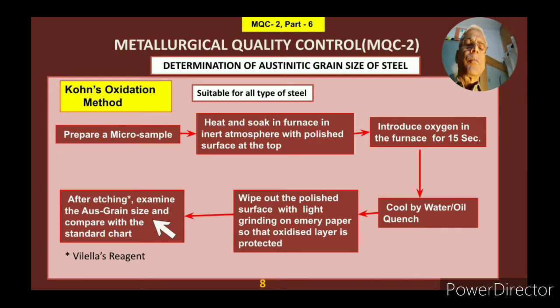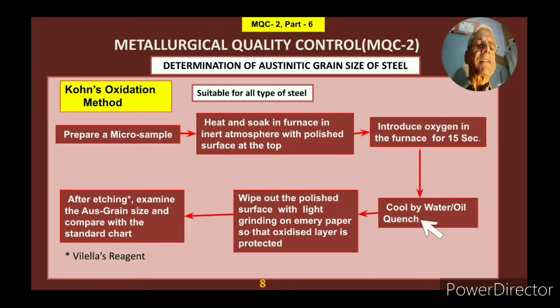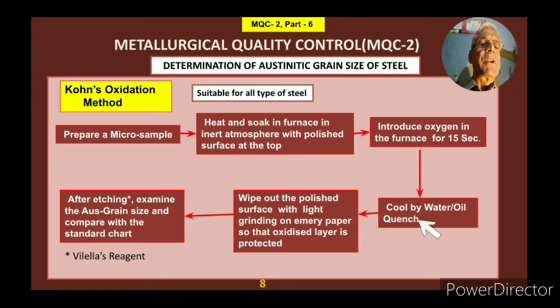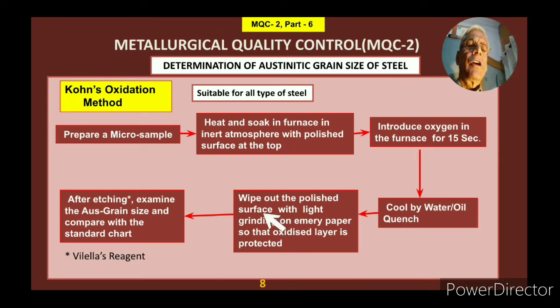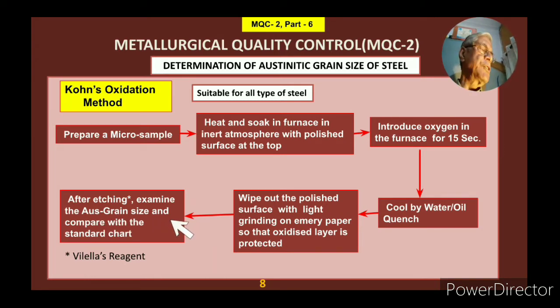In general in a metallurgical lab, we use the heating furnace from the carbon-sulfur apparatus with a combustion tube. We keep the sample in the combustion tube and then introduce oxygen through the oxygen cylinder. This oxygen causes oxidation along the austenite grain boundaries, which you then see under the microscope by etching with Villella's reagent. Villella's reagent is used for etching in the oxidation method.